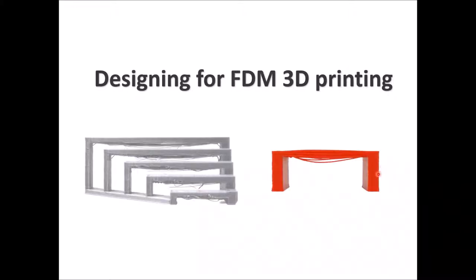We can see an example: you have two anchor points and the bridge going between them. The hanging deformation shown here is because this was the first layer printed above the two supporting areas. Since the layers were in a green state — still not fully solidified — they are slowly pulled down by gravity. The second, third, and fourth layers show these flows as well, until eventually these layers start supporting the coming layers and go almost into place.